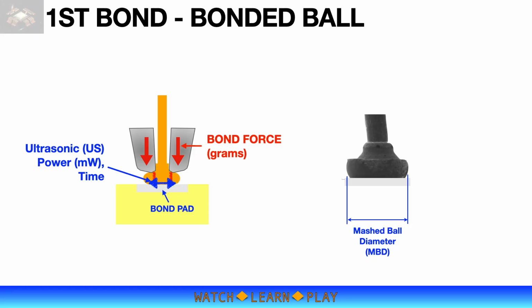On the mash ball diameter limit, while 4 times wire diameter may seem acceptable, it is possible that it is bigger than the bond pad opening or BPO. The mash ball diameter must be within the BPO, otherwise there is a risk of bond shorting to an adjacent wire.